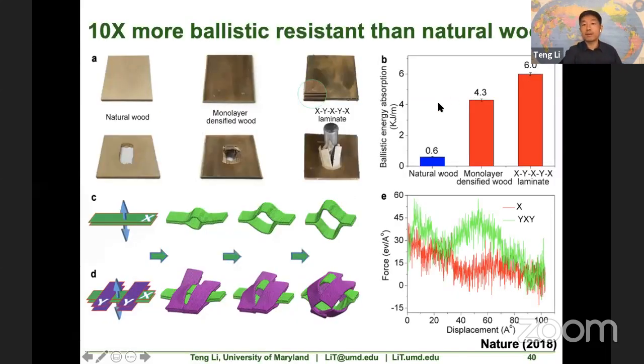Now, if you characterize the ballistic energy absorption, we can show that there is 10 times more ballistic resistance than the natural wood. And we also did coarse-grain modeling to show that the reason for this significant increase of ballistic resistance comes from this reinforcing effect of the alternating fibers in different directions.